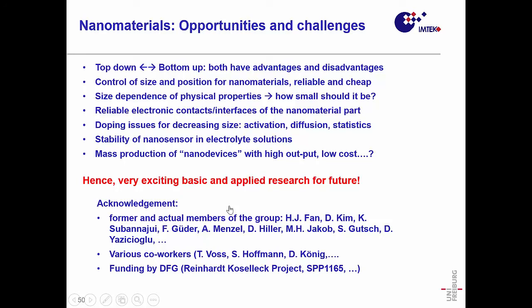Reliable electrical contacts are still an issue. At the beginning of what we did, let's say 1 out of 10 contacts were correct. Now we are better, but it's also a learning process for all of these things. Doping is an important issue: for decreasing size, you have an increasing activation energy, you have diffusion, you have statistics. Stability of these nanosensors in electrolyte solution is still an issue, and of course mass production of nano devices with high throughput and low cost. So we did it not only with these nanowires but also with ultra thin films, and also on flexible substrates. I didn't show that.